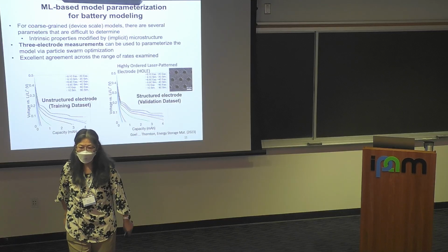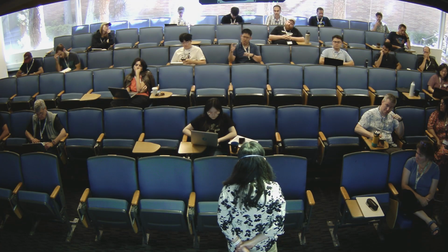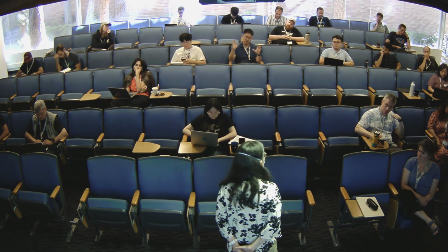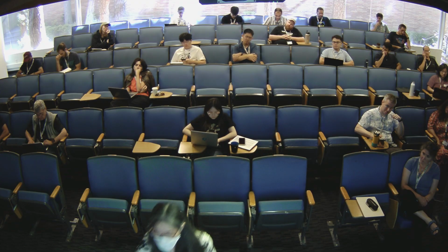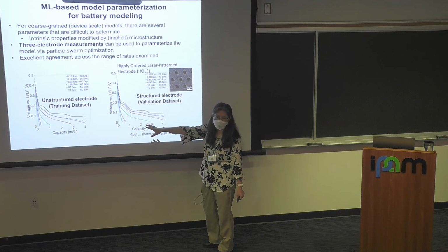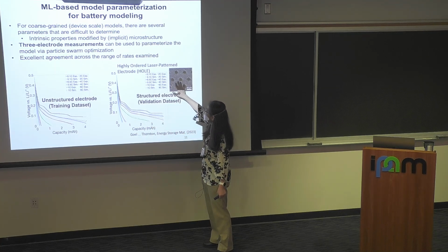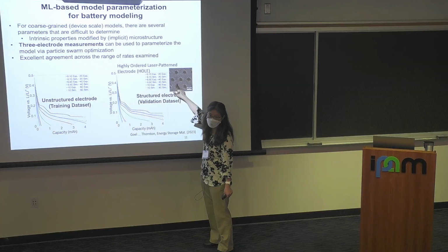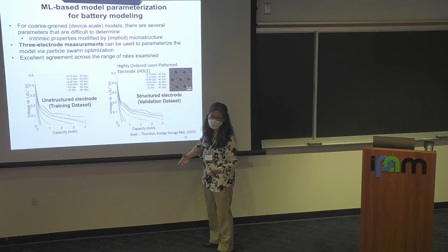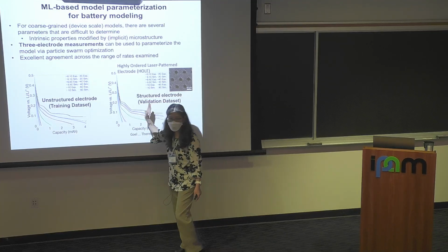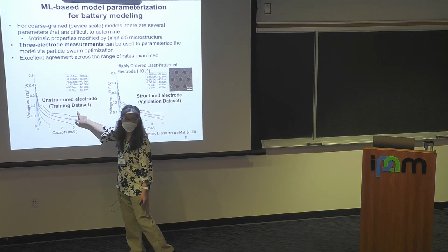So I'm just trying to understand. This means we have to change the parameters of the PDE model, the phase field, all these kind of parameters? Yeah, the phase field here. If we change those holes, if you change the size of the holes, for example, no, we don't have to. But if you change the source material for the graphite, because graphite particle size can be different depending on who you get it from, or even the specific batch, then you have to do this again.